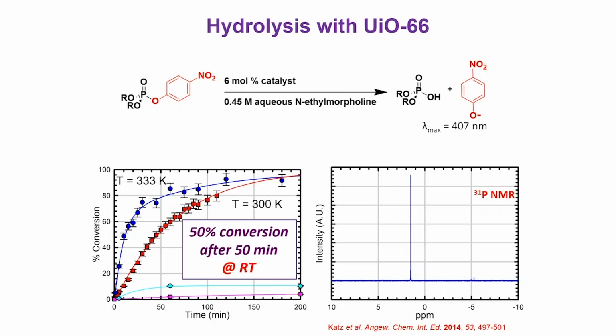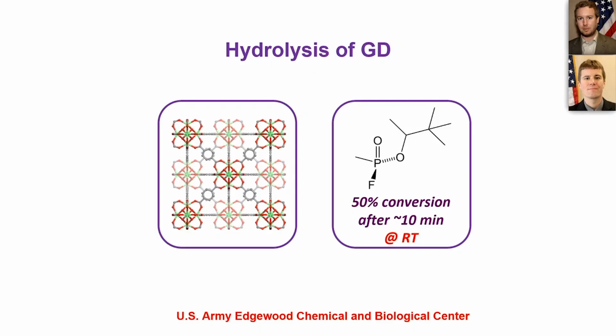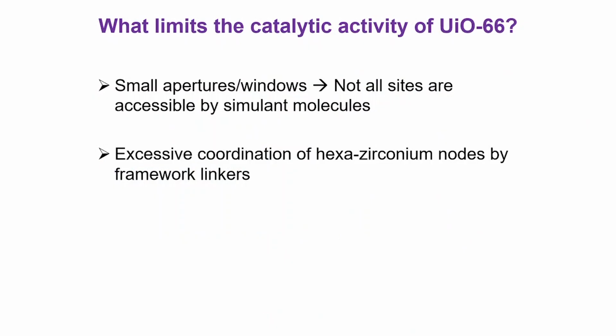But when we send this material to the Army labs, they now get a half-life with the actual agent of 10 minutes. And you might say, why is it faster with the actual agent than the simulant? Because the actual agent is more reactive, and that's why more toxic, versus the pesticides and insecticides. They are less toxic because they are less reactive, which means anything we do in our lab, we know the numbers are going to get better when we send them to the Army lab for testing. So a 50-minute half-life is fine, but there is good news and bad news. Good news, it works. Bad news, I think it's still too long.